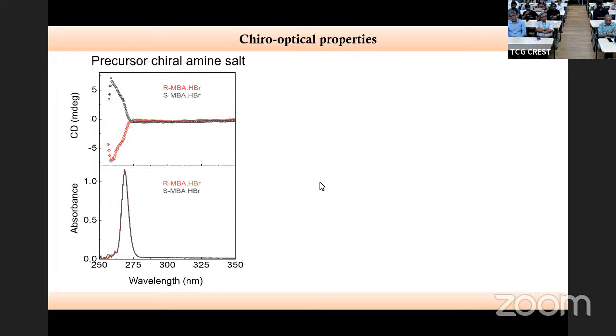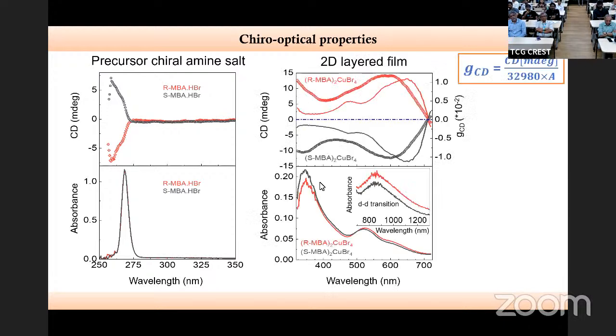The question is, do I have chirality there? Now that's the result over here. This you can see. Now look at the wavelength. It's actually some 350 to 700. So it's starting from there and going to much longer wavelength. So these are states which are completely inorganic dominated. And those states have this huge CD, depending on R or S variety. And there's a way to define this CD to be sample thickness independent, and that's defined as GCD, so that you can compare across one material to the other material, and that GCD value at the maximum is 1 × 10⁻².